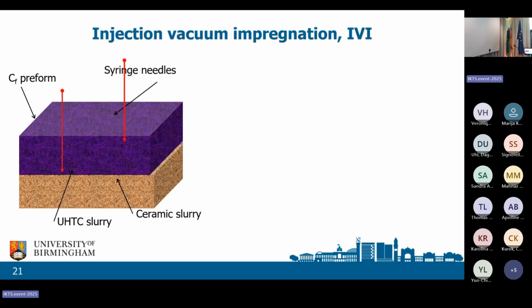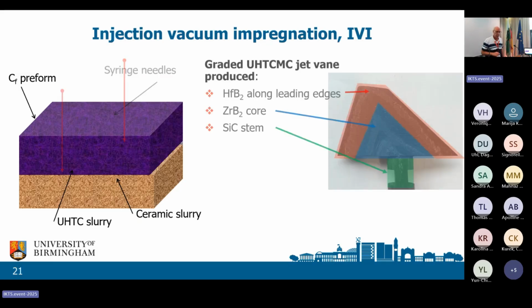Slurries mix. So you'll have a region around that where it's nicely mixed. Actually, that's really, really good because it doesn't give you a hard interface. So it's less chance of things falling apart because of it. So now you can literally put what you want where you want it. So this, you'll see this sort of shape several times. This is what's known as a little jet vane. It's about that big, so it's not awfully big.